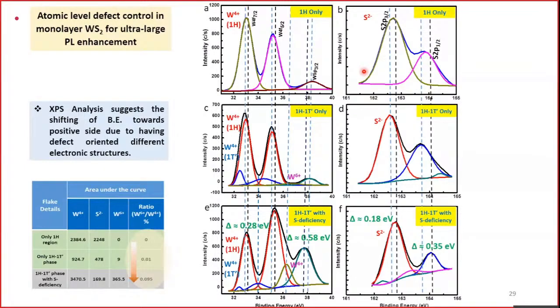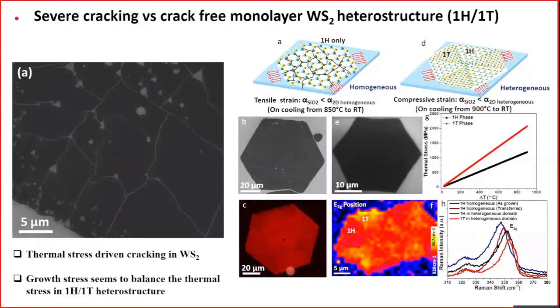Sulfur deficiency essentially introduces a small change in the binding energy in your XPS. That is consistent with the literature. In addition to that, we also see the emergence of tungsten 6+, meaning there is clearly oxygen coming in and binding with the tungsten, making it go from 4+ to 6+. Based on this, we know it is sulfur deficient and also possibly absorbed or substituted by oxygen.